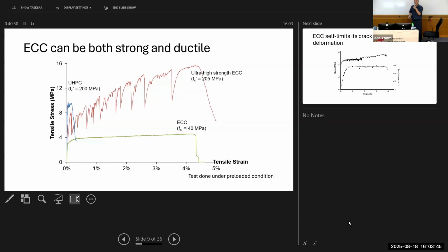Okay, so I wouldn't go and design buildings, especially like a 60-story building, today with that. We need to accumulate more experience, but it demonstrates that those ideas are feasible. ECC is a material that itself has resiliency, and there are situations when we can reduce or even eliminate steel reinforcement. And there are many good cases where you want to reduce or eliminate steel reinforcement. For example, one of the major causes of lack of durability of infrastructure is corrosion of the rebar. If it's not there, it cannot corrode, right? If you don't use rebar in the ECC, there's no corrosion problem because it can't happen. It just cannot happen, right? So there are situations when you want that in the design phase.